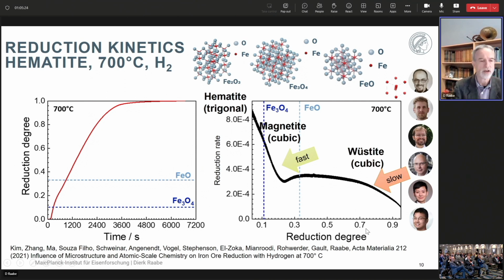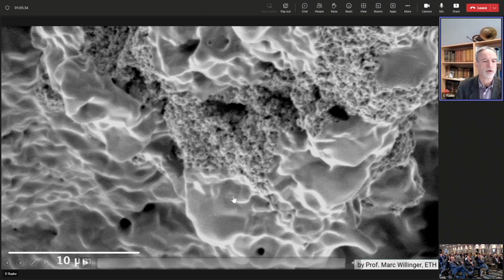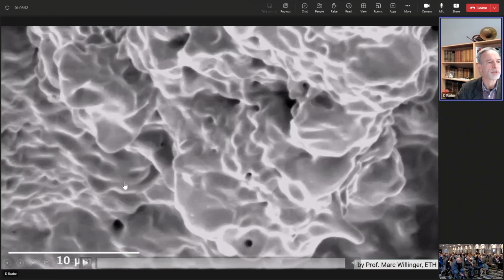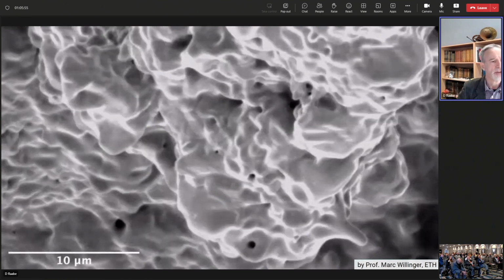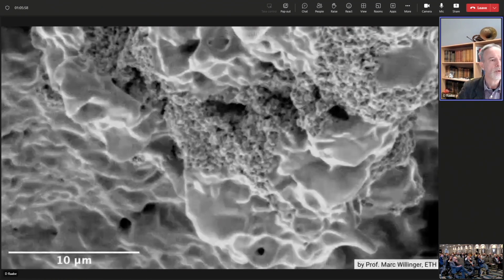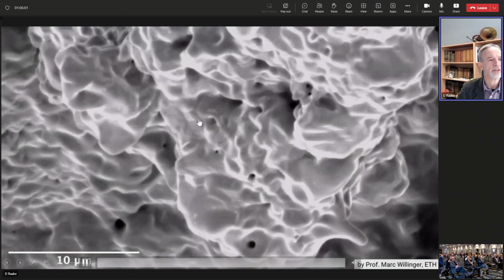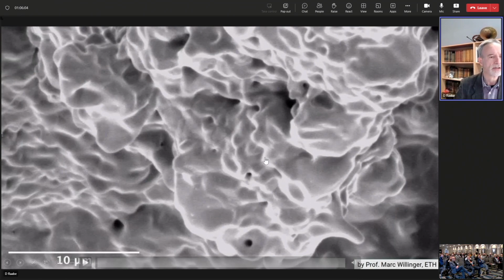And again, we keep in mind in iron, you must think big, and things that are slow are not good in iron making. So here's an example of an environmental microscopy experiment that was done by my friend, Professor Mark Willinger at ETH. He is now at the university in Munich. And he had a wüstite single crystal that we prepared, operated under hydrogen atmosphere in an SEM. And what you can nicely see, if I let this movie run, I hope you can see it, is how under this hydrogen atmosphere in the electron microscope, let me go back, this is overgrown by a dense and closely packed iron film, of course, because it's a surface-driven reaction.